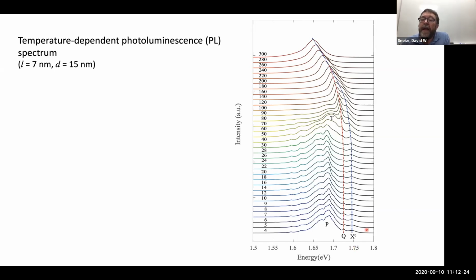Okay, so here you see the exciton line. And that's exactly where it should be. And there's a band gap shift. So that shifts down to the red. That's called the Varshni equation. And also, as you can see, as temperature rises, there's a line broadening due to phonon interactions.